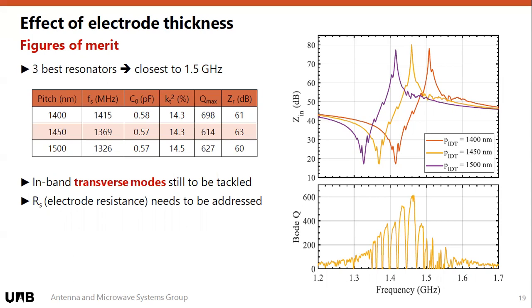Here we have some data from these resonators. We measured the Q of each resonator, and we had an interesting Q max of around 600, 650. An impedance ratio, the ratio between the maximum and the minimum impedance, so your impedance at FS and your impedance at FP, of 60 dB. That is really interesting. In order to build filters, you want the maximum impedance ratio you can have. And we are obtaining a KT squared of 14%. In the initial figure, we said that aluminum nitride BAW resonators provided a 6.7% coupling. You couldn't go way above that because of AlN and its C33 parameter. And lithium tantalate SAW was providing 8.5, and that was it. So now we are going well above that.